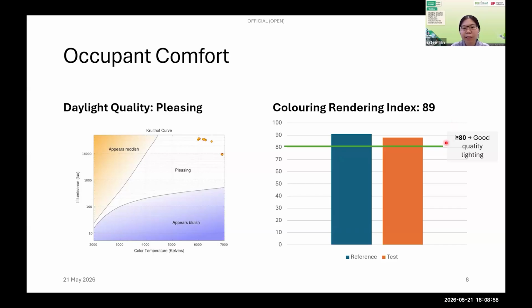A CRI above 80 is considered good quality lighting, and our coating had a CRI of 89. This means that occupants will still perceive colors accurately and naturally. The coating doesn't cast a tint or distort the indoor environment. So in short, the coating reduces heat and glare without compromising the quality of the indoor visual environment.